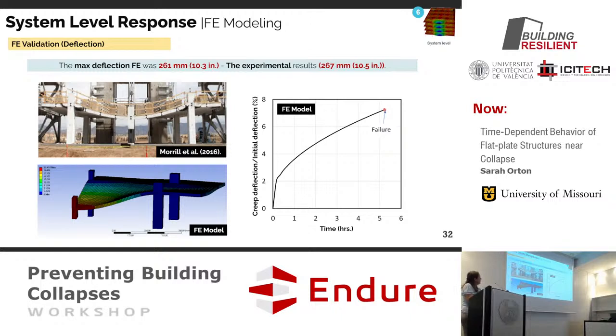removed a column and it deflected. This is actually 4 hours after the test. 4 hours later, it had punching shear failures at these connections, and then they're like, okay, it's fine. They went away. Overnight, it completely collapsed. And so it's this idea of under the sustained loading, it initiated a punching shear failure, and then it collapsed overnight. And the model was able to match that fairly well. They didn't have a lot of data at the collapse because they shut everything down and went away for the night. But I think I was able to match the results fairly well.